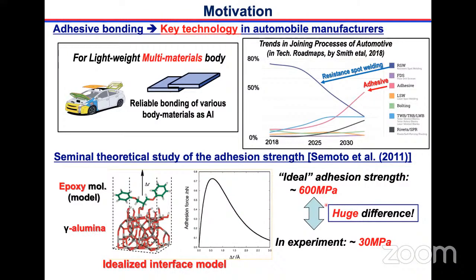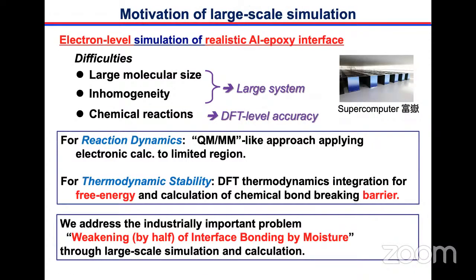The ideal adhesive strength from the derivative of this curve is 600 megapascal, but in experiment it is only 30 megapascal. That means a more than 20 times difference, a huge difference exists. Because of that, we want to have a much more realistic analysis theoretically.